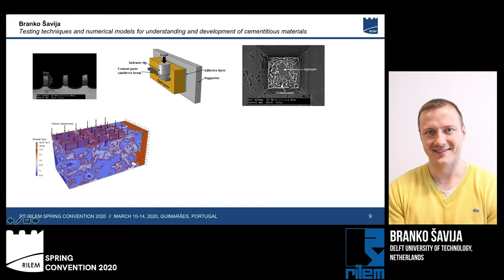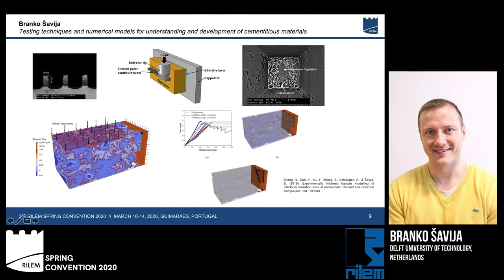But again, in order to get the mechanical properties of this very thin interface, we need to use a combination with numerical simulations, because our measurements give us a global response of the microvolume. Simulations will enable us to get the local response of this contact. Again, fitting the numerical simulations to the experiment allows us to mimic the global behavior. And then, again, from here, we can derive constitutive equations that we can use in higher scale simulations.